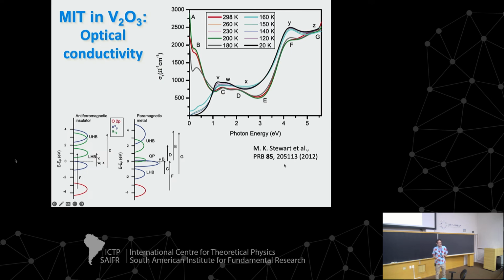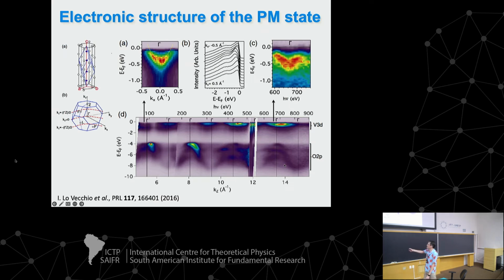And I will explain shortly why only in the metallic state. This is data obtained by the group of Alessandra Lanzara not so long ago. And this ARPES data was measured in both the basal plane, the hexagonal basal plane, and perpendicular to that plane. And in all cases, what is clear is that there is an electron-like pocket around the gamma point that you can see here, either in measurements along the basal plane or in measurements perpendicular to that plane, okay?